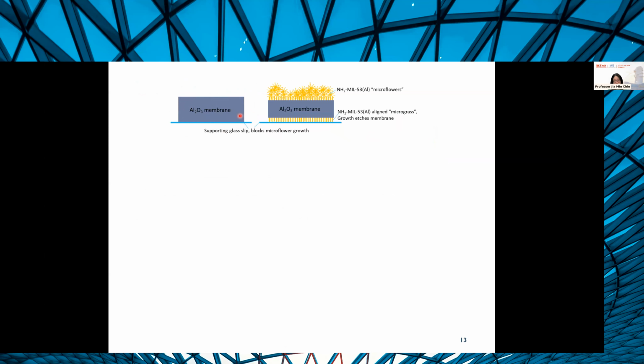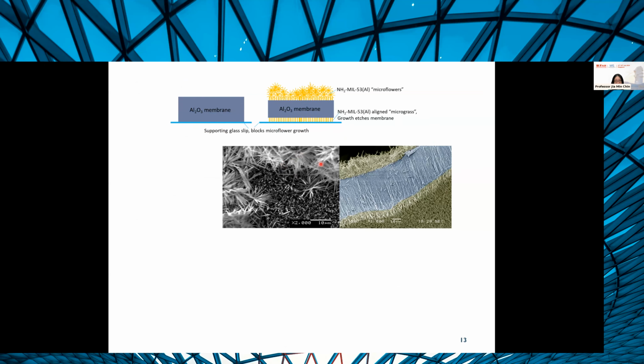So this AAO happens to be porous, right? So the ligand can go through and start to react. And so this actually reacts both on the bottom side as well as on the top side. And so the growth starts to etch the membrane, and it starts to grow this monolayer of micrograss. And what you see is something like this. So on the top, you have microflowers that are growing on top of a monolayer of these micrograss.